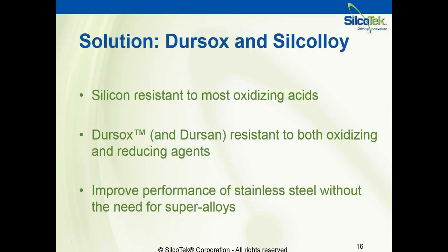So again, both our Dursox and Silcoloy coatings will work well for resisting most of the acids and different sorts of corrosive media that are present in a semiconductor manufacturing process. Even outside of a plasma environment, many of the process gases are non-reactive. You'll see that the Dursox and our Dursan coating are both resistant to both oxidizing and reducing agents, and they're upgrades to stainless steel compared to super alloys. So you'll get a similar performance that you would with the corrosion resistance of a super alloy at a much, much cheaper cost with the coating on stainless steel. Not to mention that with the exotic alloys like Hastelloy, Monel, etc., you have issues such as copper and nickel content, which even though they are great alloys, they still present problems for device manufacturing.